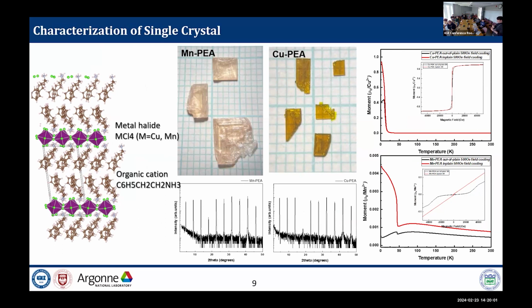In this result, we made quasi-two-dimensional crystals with this structure, from the XRD. And we have quasi-two-dimensional Heisenberg ferromagnetic and antiferromagnetic behavior from the magnetic measurement. We get in-plane ferromagnetic ordering and out-of-plane weak antiferromagnetic ordering with hysteresis in PEA copper tetrachloride, and in-plane very weak ferromagnetic ordering and out-of-plane antiferromagnetic ordering with a spin-flop transition near 3.5 Tesla in PEA manganese tetrachloride. Also, not included in this slide, we can observe abnormal absorption in PEA copper tetrachloride due to the d-d transition from the Jahn-Teller distortion.